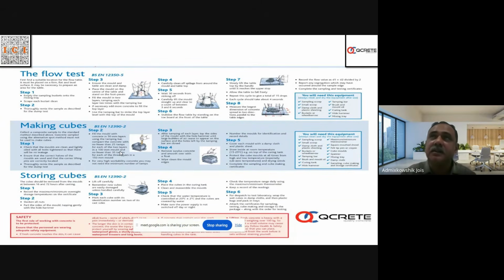And very clearly, IS 4926 gives the frequency of sampling: for 50 batches or 50 cubic meters, one set of sample, which is 6 cubes, 3 for 7 days and 3 for 28 days. So if we take one sample meaning 1 cube, it is not standard. Each truck taking one sample, randomly asking you to take 2 cubes, or when the concrete is already almost discharged, at the end there is some slurry. If the customer takes the cubes in that kind of situation without following a proper procedure as described here, it may lead to apparent strength issues.